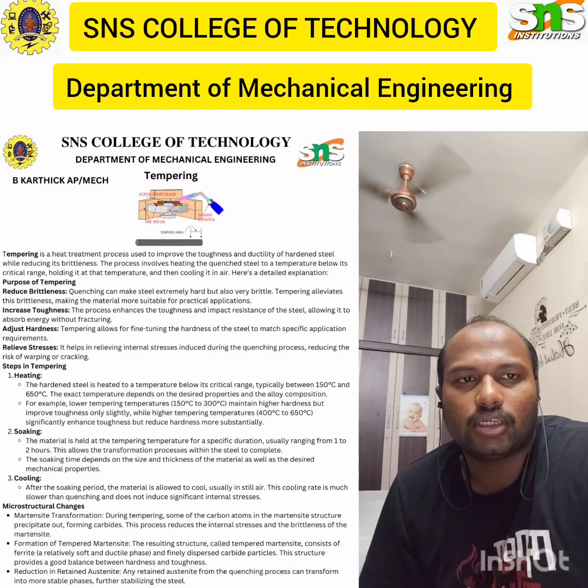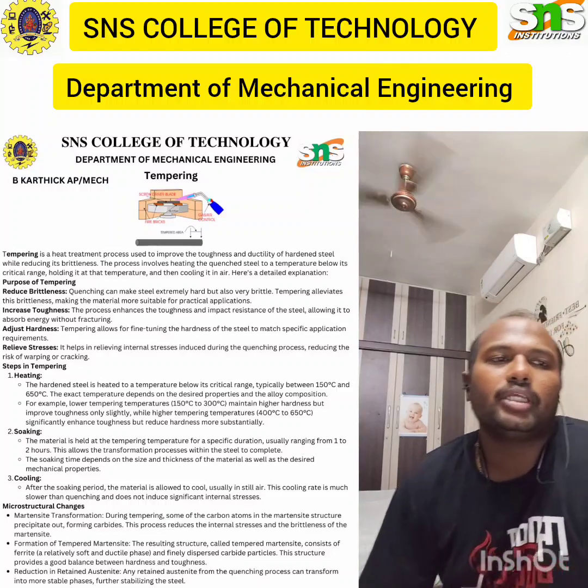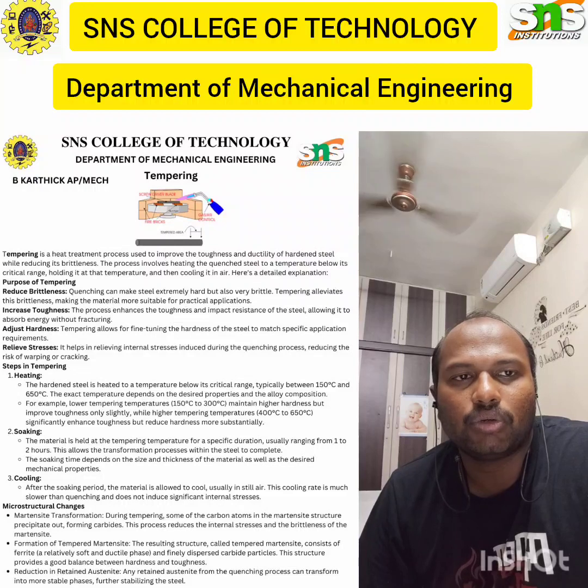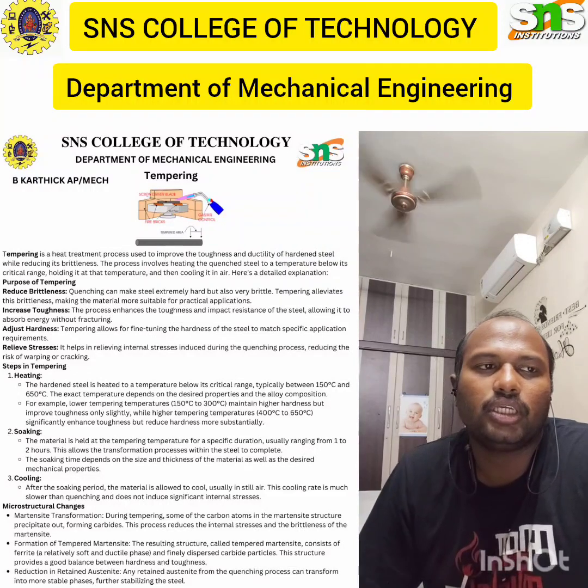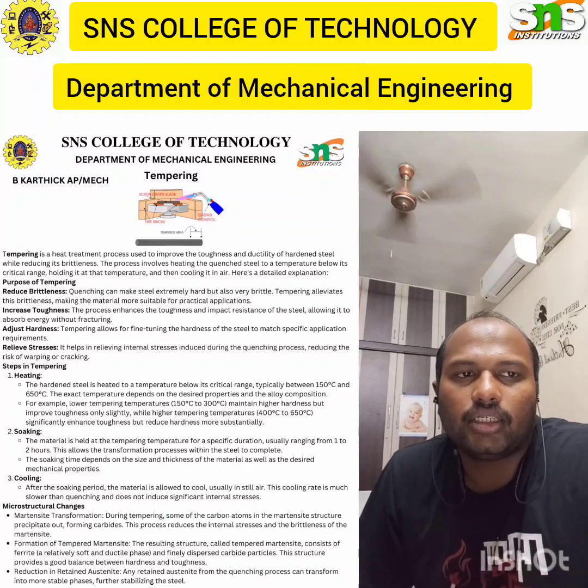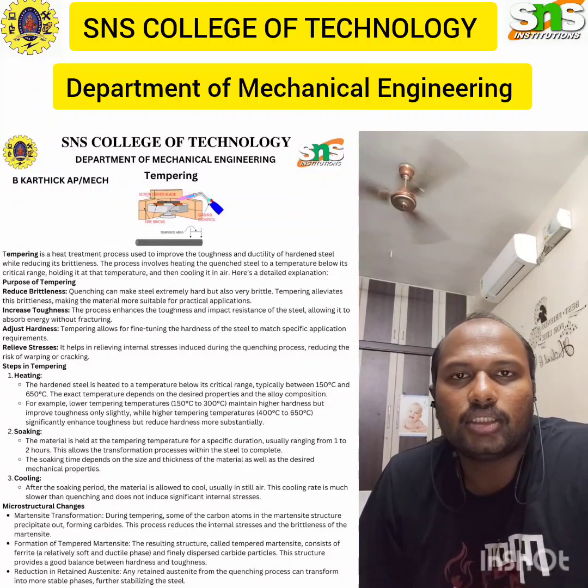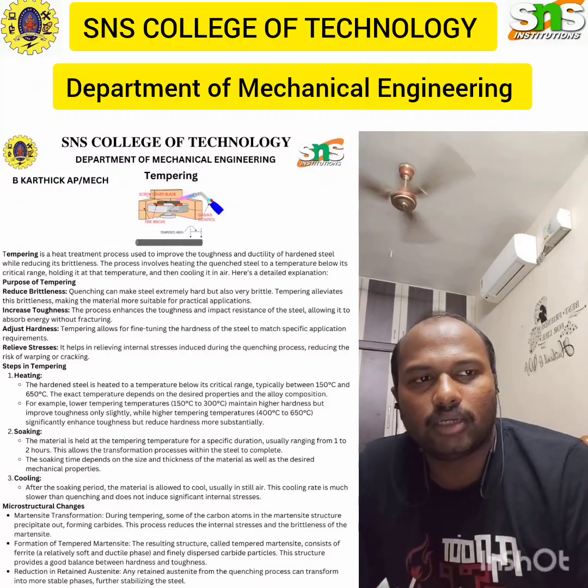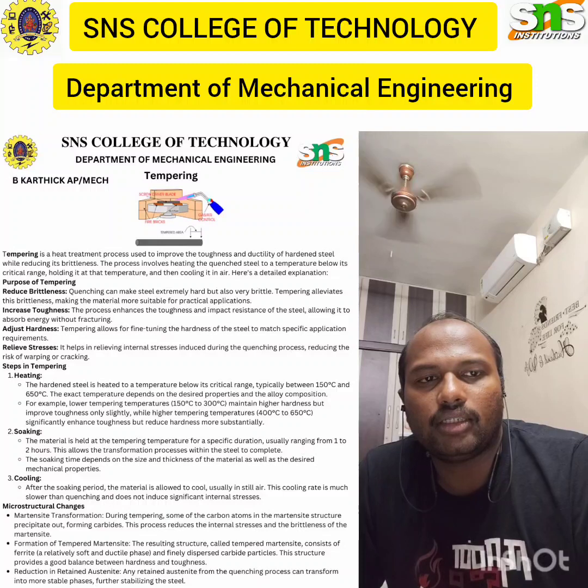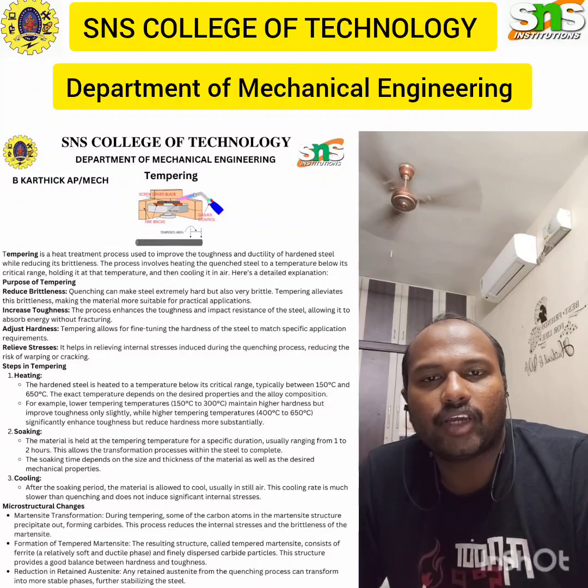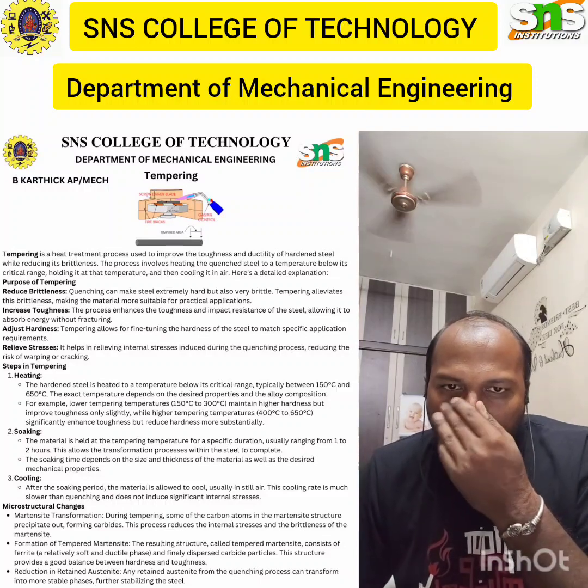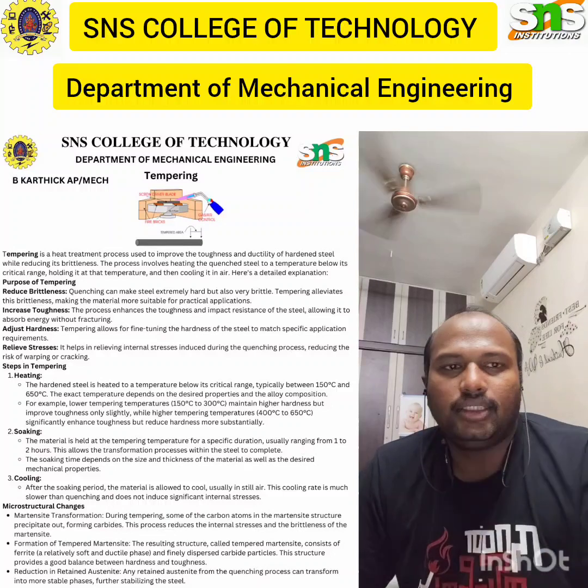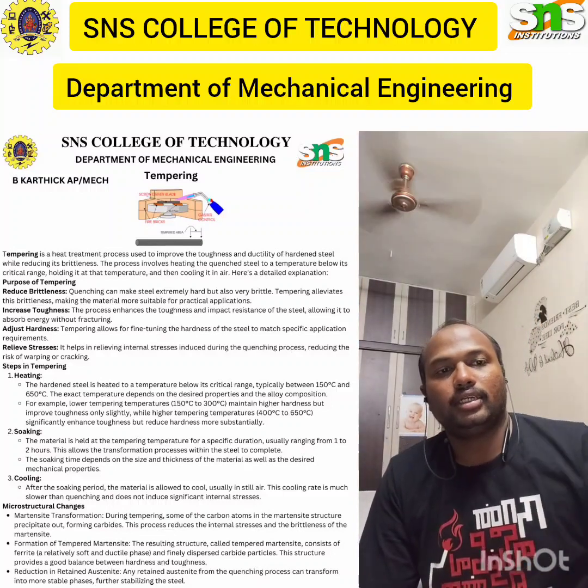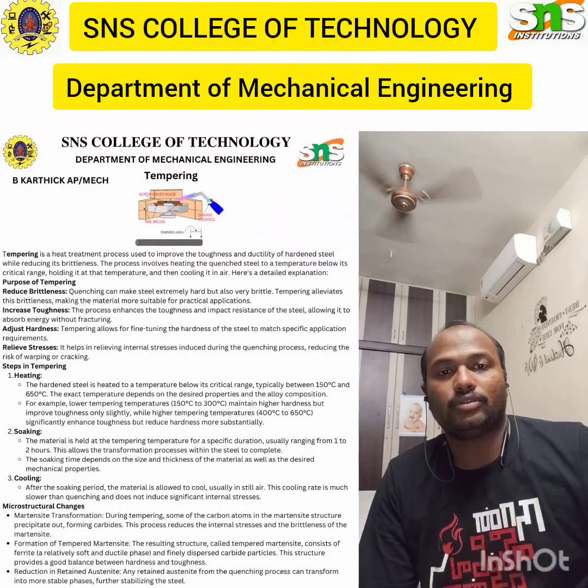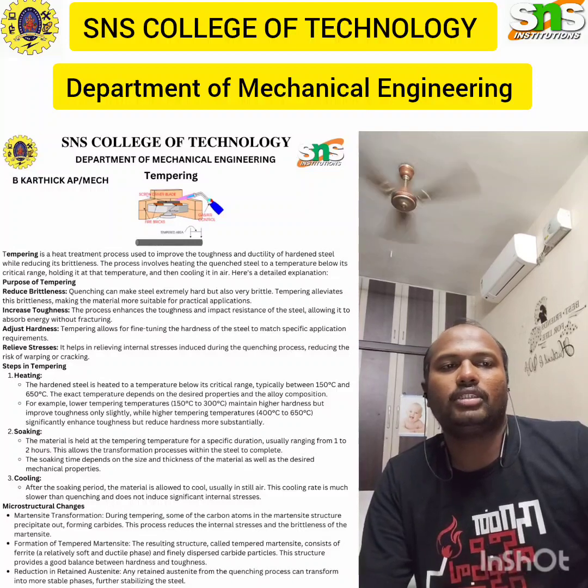Microstructural changes. The first one is martensite transformation. During tempering, some of the carbon atoms in the martensite structure precipitate out, forming carbides. This process reduces the internal stress and brittleness of the martensite. Next, the formation of tempered martensite. The resulting structure, called tempered martensite, consists of ferrite, a relatively soft and ductile phase, and finely dispersed carbide particles. This structure provides a good balance between hardness and toughness. Then, reduction in retained austenite. Any retained austenite from the quenching process can transform to a more stable phase, further stabilizing the steel.